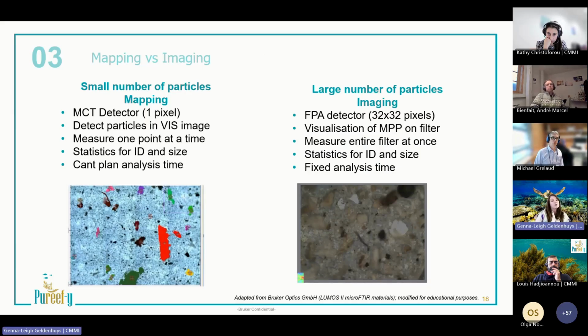So there are two potential pathways for microplastic analysis by micro-FTIR, and that is chemical mapping or imaging. For mapping, you would use an MCT detector and measure one point at a time or a line after detecting particles in a visual image. And it's important to note that this image needs to be a good image of high quality. As Olga mentioned, no overlap and no agglomerates, and also if the particle is transparent, it can be an issue.